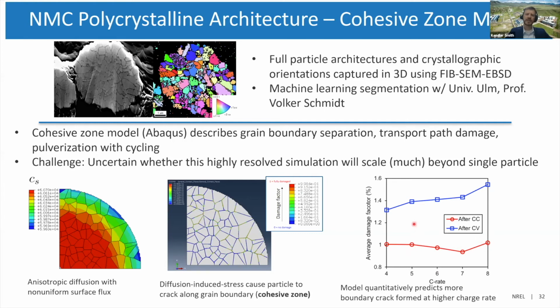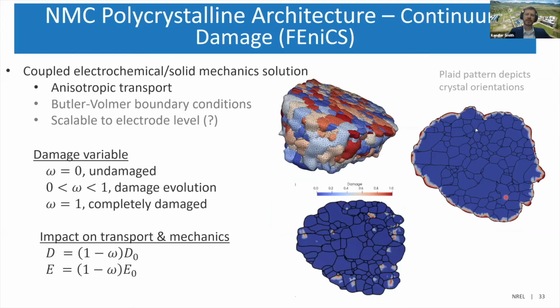But if you do continue into the CV range, then the cutoff is later and you do see some dependency on the damage. So we're working to both scale this up to 3D and validate this model, tune all the parameters. And soon thereafter, we hope to also go on to 811 high nickel materials, which have even more damage.